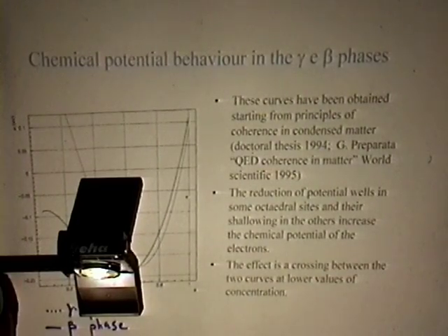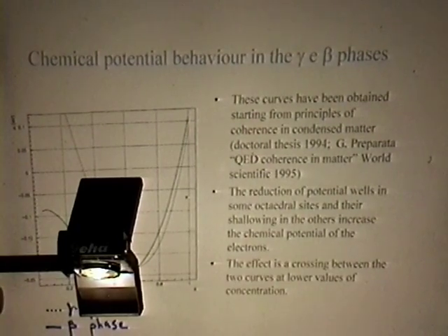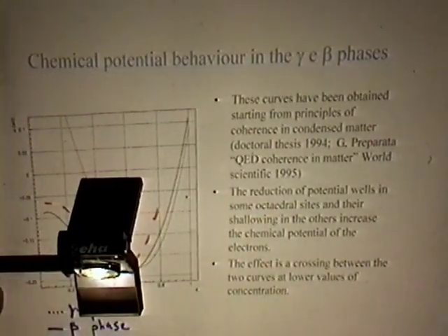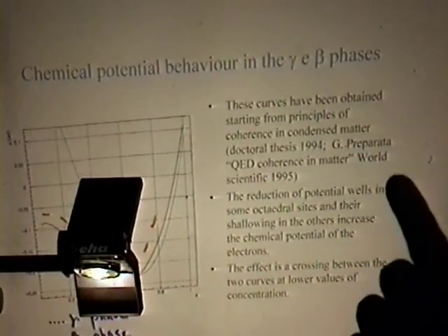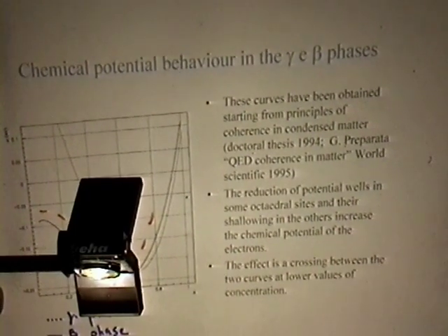So what happens is that the reduction of the potential wells in the octahedral sites, and their shallowing, has the effect of increasing the chemical potential in this way. So what you see is that the crossing to the gamma phase chemical potential curve occurs at lower concentration. The gamma phase starts to nucleate at lower concentration. This moves the maximum of the Baranowski curves towards lower concentration. It is what we saw in literature. It is what we saw in our experiment.